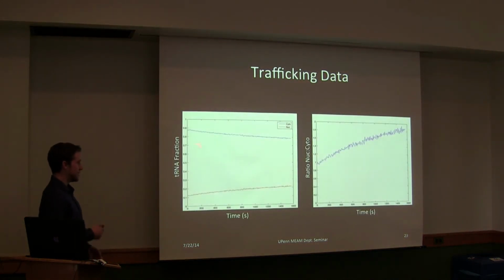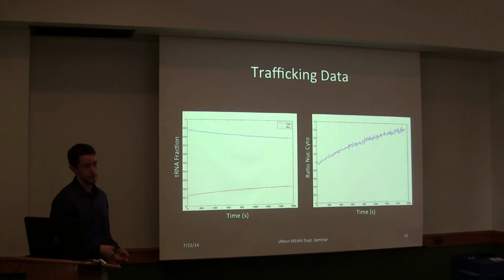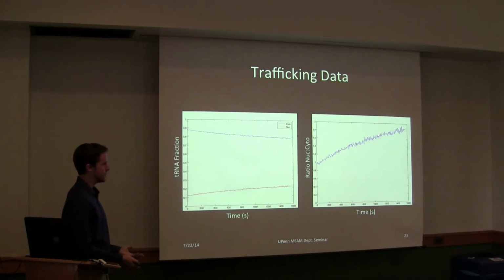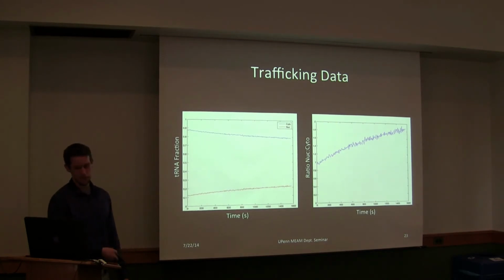And you can look at things like the tRNA fraction, so of the total fluorescence, what fraction is in the cytoplasm and what fraction is in the nucleus. And here we can see it almost doubles over time, from about 10% to about 20%. We could also look at the ratio between the mean intensity. And from this data, we can then fit time constants. So for example, with these cells, it was on the order of about a half-hour time constant for equilibrating the concentrations in the cytoplasm versus nucleus.